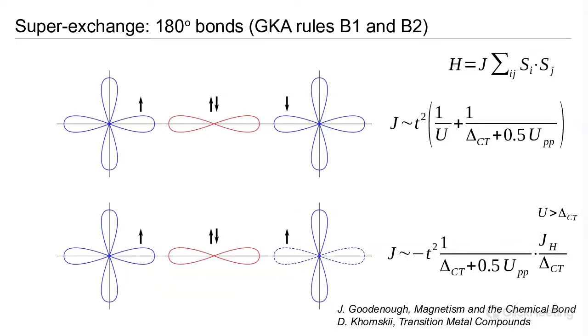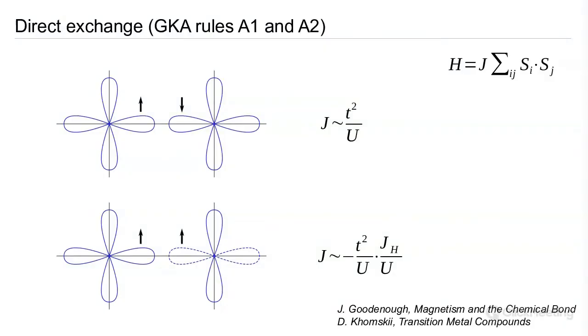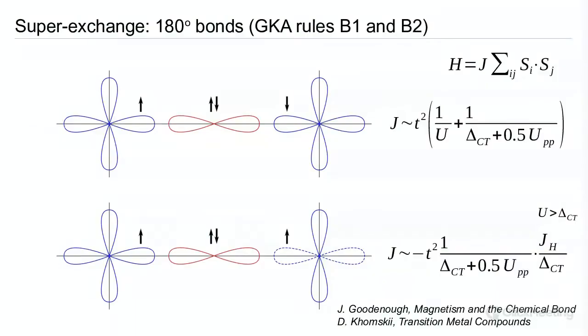And then if we go to the next example where we have an unfilled orbital, again, this is shown by this dashed line here, we could apply a similar logic, and essentially what can happen is a spin-up electron can hop from the oxygen into that orbital. That can then Hund's couple to the rest of the unpaired electrons on that site, and then the spin-up electron on the left can then hop into the oxygen in the middle, and vice versa. So we have here an effective ferromagnetic exchange. So it largely mirrors, actually, if I just flick back, the results that we obtained from the direct exchange case, but we just have it scaled differently.